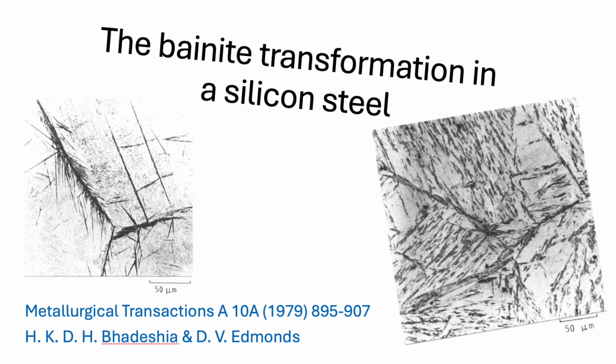Metastable phase first. Yes, which was then later replaced by the more stable cementite. This whole sequence, ferrite forms first displacively, carbon gets pushed into austenite, then carbides precipitate later upon tempering, reinforces that carbide formation is secondary, not primary, to the main event. Okay, upper bainite strongly points to shear.